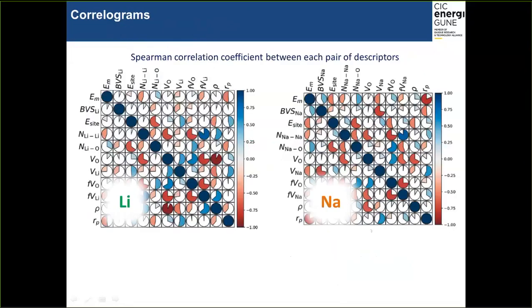So these are the Spearman correlation coefficients between each pair of these descriptors for lithium and sodium oxides in this case. And some correlations have a very clear physical origin. For example, the negative correlation between the migration energy and the percolation radius is quite obvious because the percolation radius measures the bottleneck of the diffusion channel. And an increase of the percolation radius reduces the repulsive forces at the bottleneck, and therefore this reduces the migration energy.